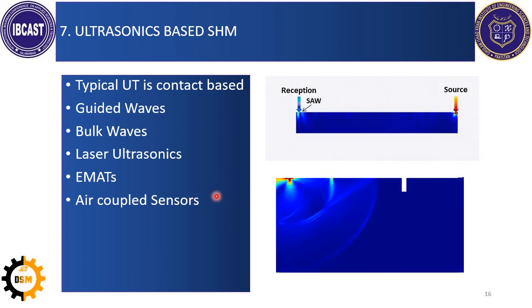Then last we have the air coupled sensors, which can work at larger distances away from the surface as compared to EMATs. But the problem with them is that the amplitude and the strength of the guided waves should be very good because they are in the air, and in the air the intensity of the signal is attenuated very quickly.